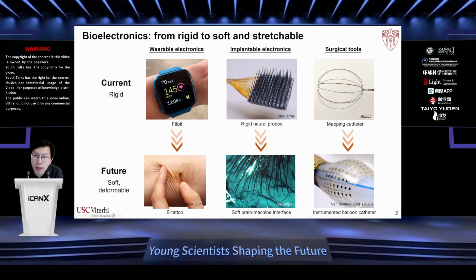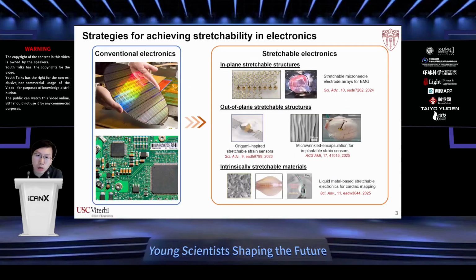So with all these advantages, how can we develop stretchable bioelectronics? We know conventional electronics are manufactured using standard integrated circuit microfabrication technologies, which are planar and use mostly rigid materials. In order to develop stretchable electronics, we have different strategies. In our lab, we focus on applying structure designs to existing rigid materials. Showing the first 2 examples, we can leverage in-plane stretchable structures and out-of-plane stretchable structures to give intrinsically non-stretchable materials some device-level stretchability. And in the last example, I show that we can also use intrinsically stretchable materials, in this case gallium-based liquid metal, to develop intrinsically stretchable structures and devices.